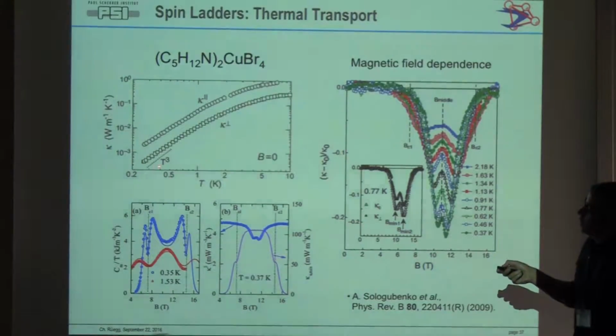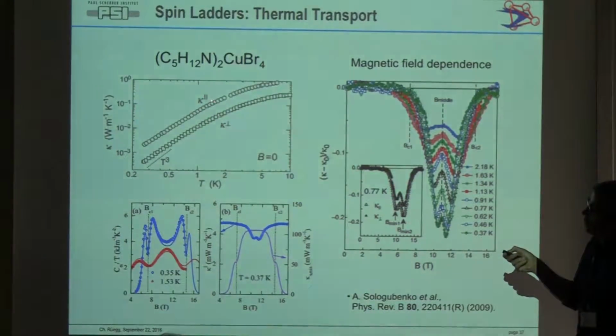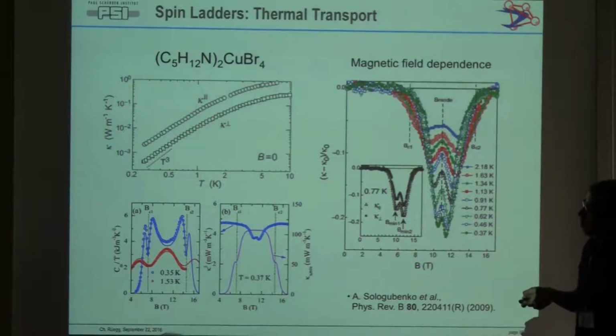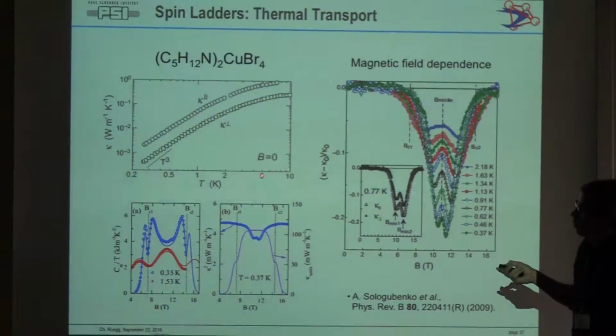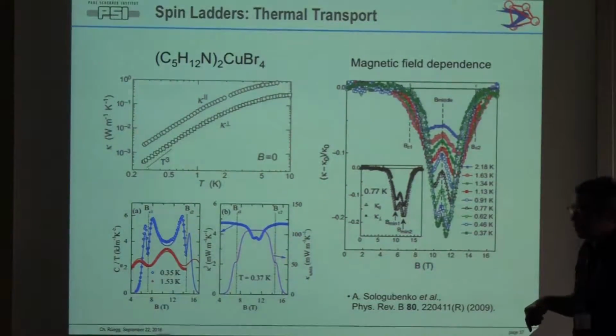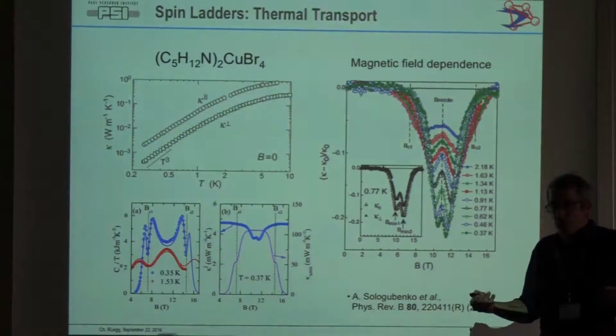So first of all, you see that the anisotropy for the thermal conductivity is rather small for situations parallel and perpendicular to the ladder. That was very disappointing, and we never really understood why. So what we went on to do is to calculate what we would actually expect for the thermal conductivity in just an effective spinon picture.